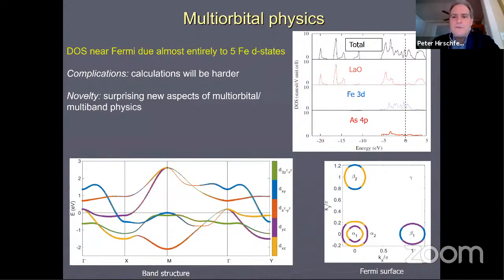What's interesting from a theoretical point of view, what's different about these materials is that although they involve these states at the Fermi surface, like the cuprates, there's several bands present and several orbitals, several d orbitals present. Here on the right, you can see a density functional theory calculation for the total density of states, and most of it comes from these iron 3d states. Very little of it comes from arsenic states, which is a few eV below. And you see this plot of the band structure with different colors showing you the orbital weights of each d state. And if you plot the Fermi surface, you see that even each sheet on the Fermi surface has a varying orbital weight as you go around.